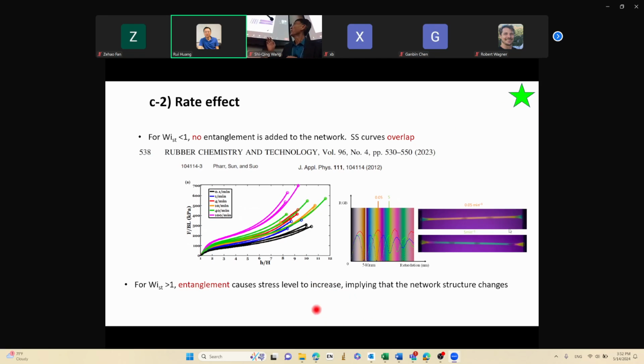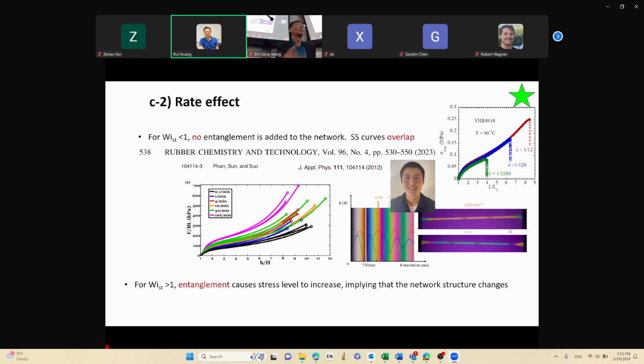What does this really mean? This is Zhigang, you popularized that 3M sample. We use it day and night nowadays. So what happens? If you do birefringence, you show the reason the stress is higher at higher rate is because I can pick up entanglement contribution now. Michael will love it. Okay, and you show the birefringence is higher because you pick up a different network structure. But to your disappointment, when you go to 90 degrees of the 3M sample, the curve collapses because the temperature is so high, your external rate can never be high enough in this range to pick up entanglement contribution.